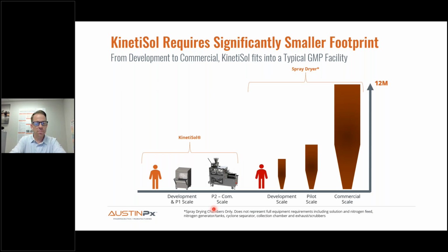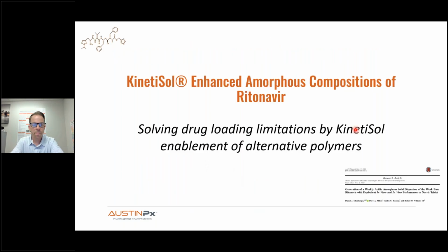For the sake of time, I'll probably skip over this, but I've already kind of described how the scale up is very straightforward with KinetiSol. We go from research scale to manufacturing scale, and that'll take us from phase 2 to commercialization. And this equipment is portable. It can be placed anywhere. The utility requirements are electricity, chilled water. Contrast that against spray drying, where you go from a Büchi all the way up to a PSD 4 or 5 by the time you're at commercial scale. There's so many scale-up events, so many challenges in terms of changing particle size, how that affects downstream processing, secondary drying, roller compaction. There's a lot of challenges you face for spray drying that we just don't have with KinetiSol.